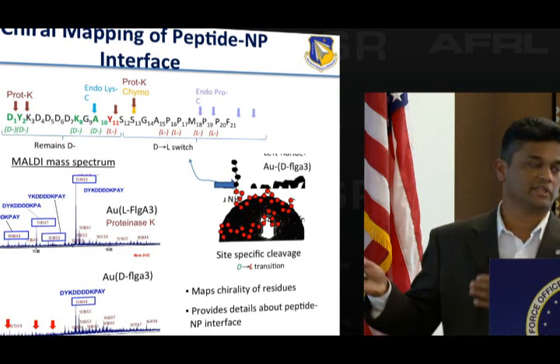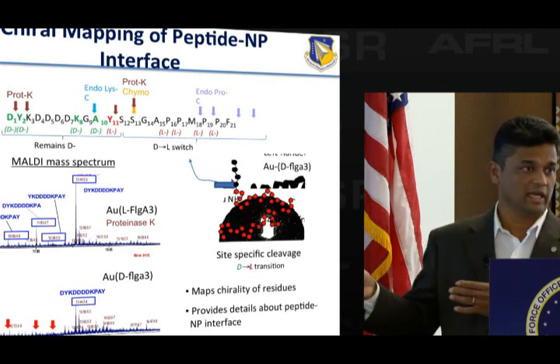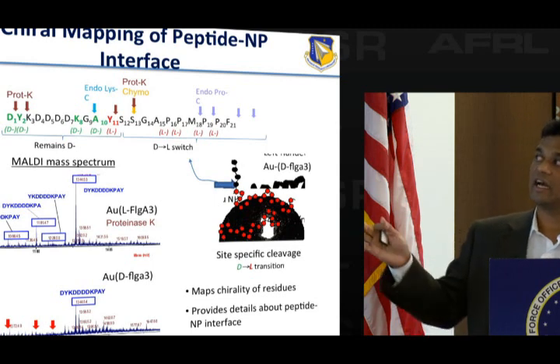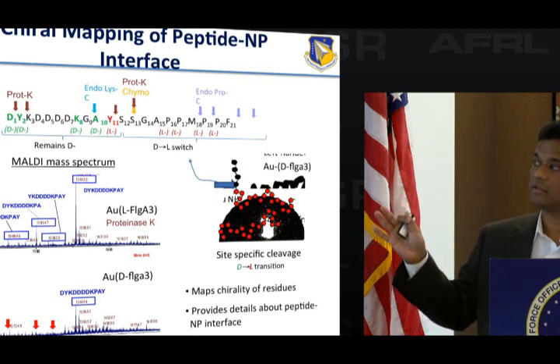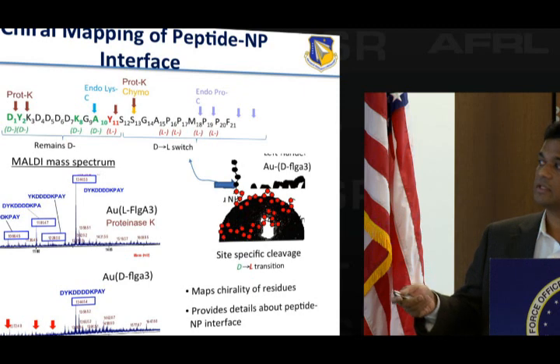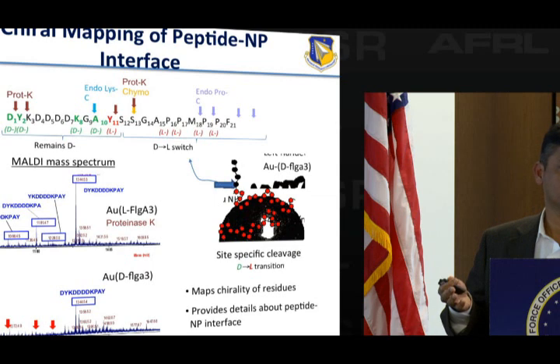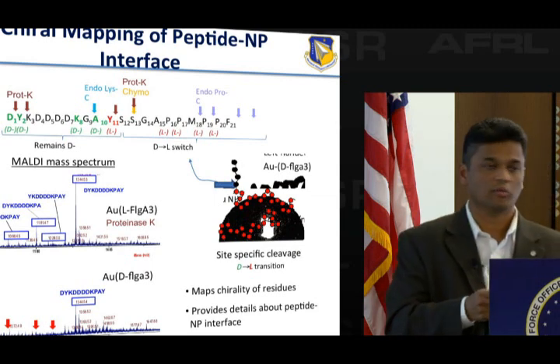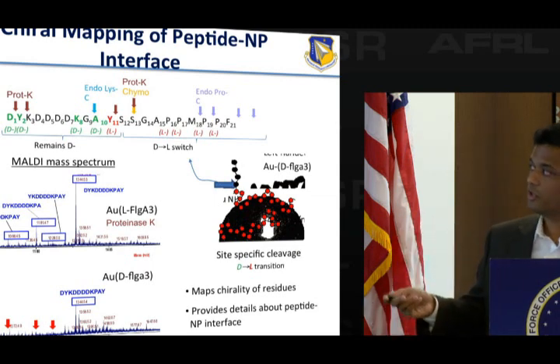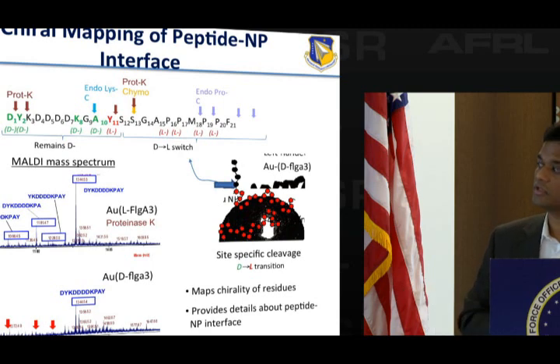So chemically, we know it's an inversion because the enzyme is seeing it. And we can take other enzymes and throw them with gold nanoparticles, or use nonspecific peptides, and we don't see the same thing happen. The key is that the peptide has to bind to the gold surface. And this interaction is not through a thiol. This is through non-covalent interactions. If you use a thiol linkage to pull it down to the gold nanoparticle, we don't see it. So we only see it if there's close contact with the gold surface.